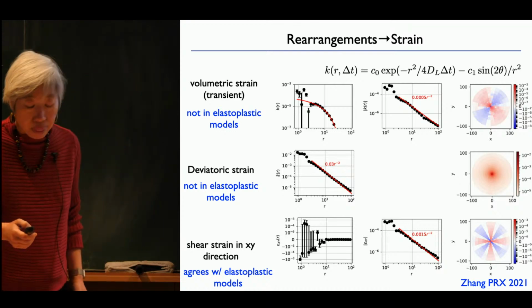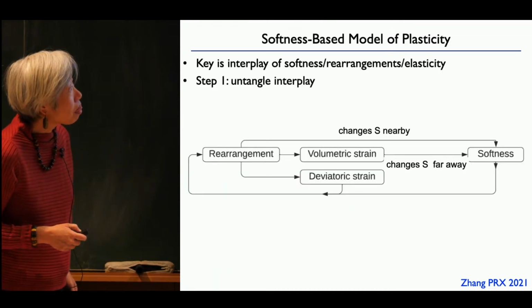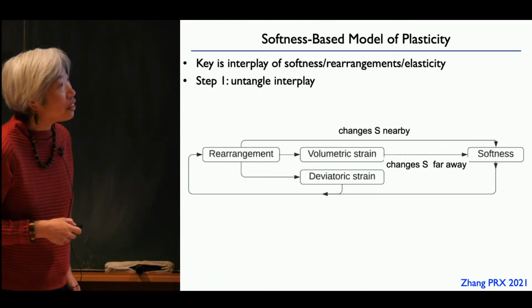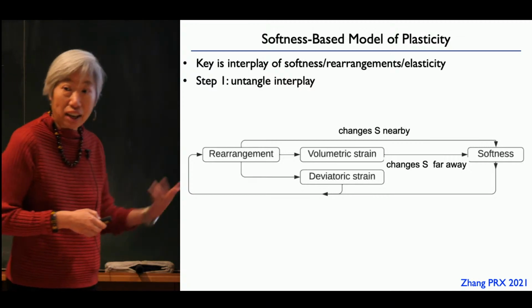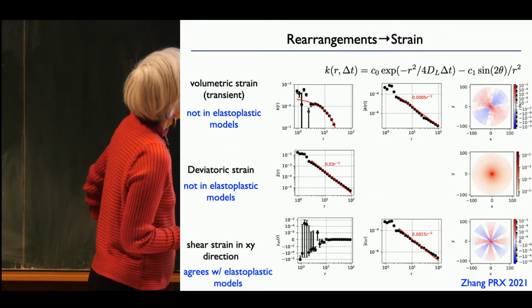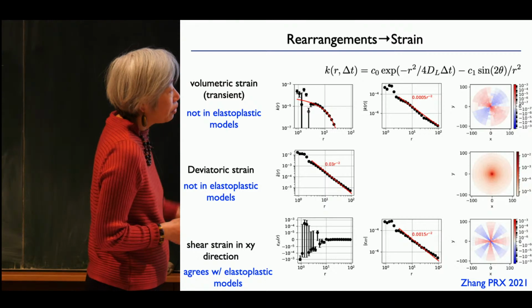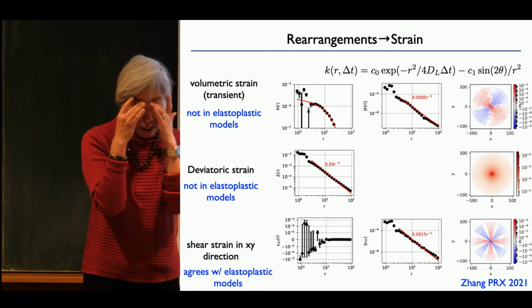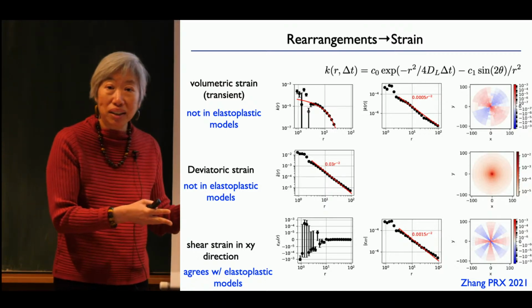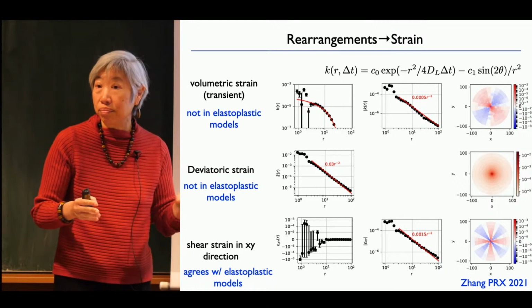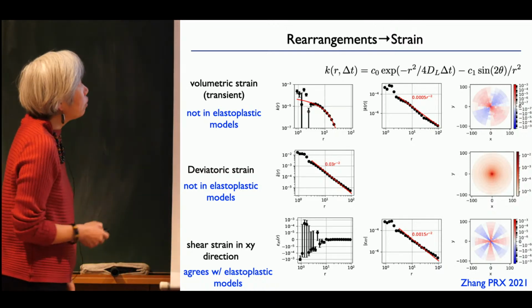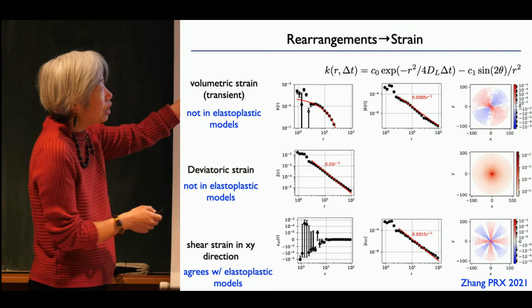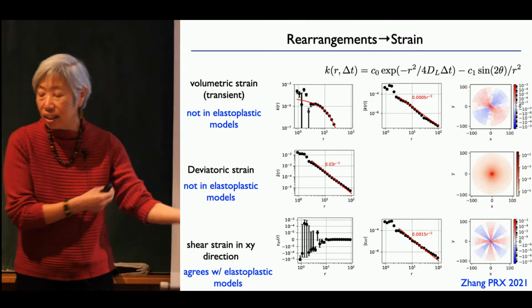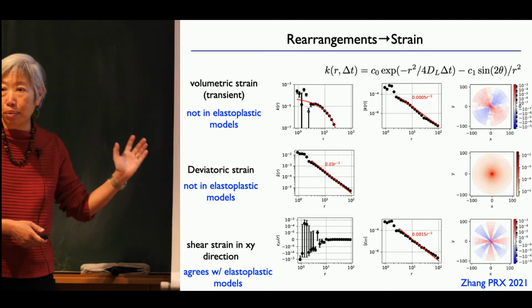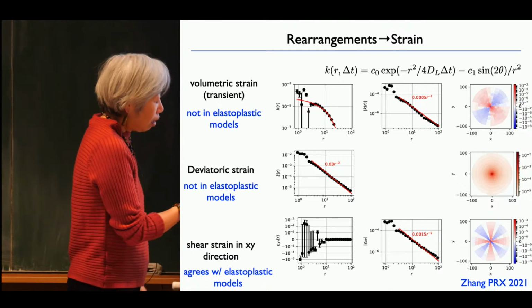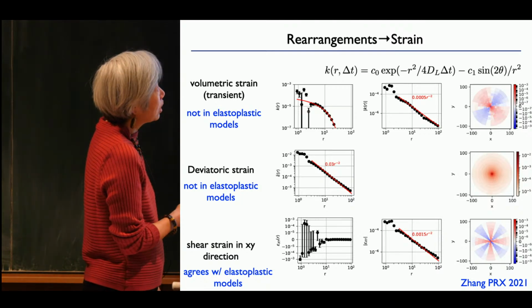Why the deviatoric strain doesn't change the softness? Why only the... That turns out to be a much smaller effect. I see. Yeah, and I'll just show you. So here's how we do it. What I'm laying out is a framework that we then just use for each system. Okay, so what you do, and these particular plots are taken for a system of Hertzian jammed particles, okay, under athermal quasi-static shear.